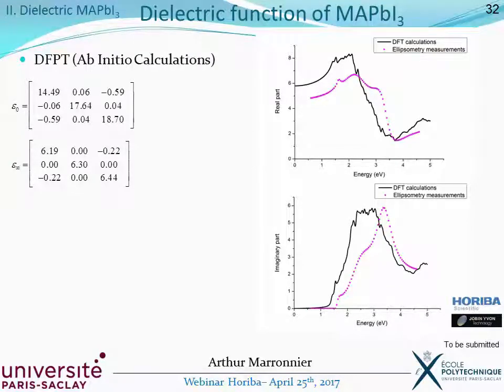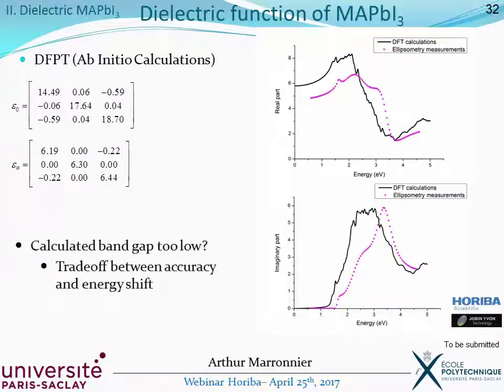Especially if you look at the imaginary part, you see that the band gap seems to be too low for our calculations. Actually, this results from a trade-off between the accuracy of this black curve and the energy shift we have. If we want not too many oscillations in the black curve, if we want a nice smooth black curve, then unfortunately we're left with an energy shift to the left. But I did some energy band calculations, and I checked that it was the right band gap for our materials and found the right 1.55 value.